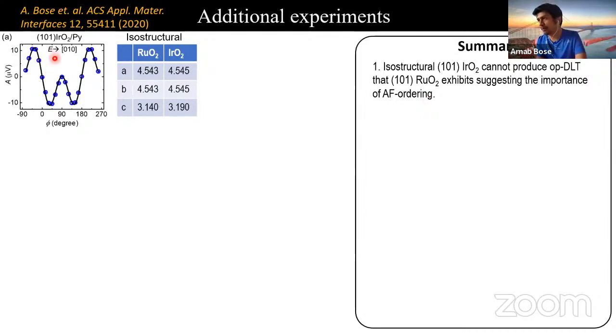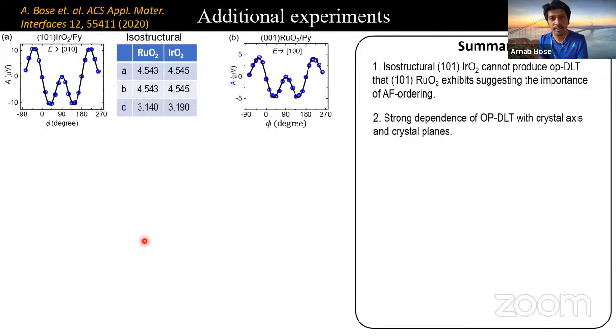However, iridium dioxide itself can be quite interesting because it also hosts Dirac nodal lines and shows anisotropic spin Hall effect, which we studied in this paper. You can refer to this for more details of iridium dioxide. We also studied other planes of ruthenium dioxide, such as the 001 plane. In that plane, we do not observe any extraordinary torques, which is also consistent with the theory, because it is not theoretically expected to see extraordinary torques in the 001 plane, meaning we have very strong crystal axis and crystal plane dependence of the torques.